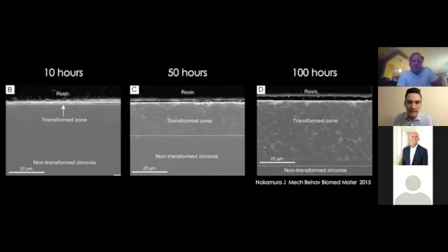We tried to study it, and I was interested in it. And the crowns that we got back from wearing in the patient's mouth for a year, we sectioned through them and tried to see any surface cracking, and we couldn't even find it. It was too small to even see. So I don't get too excited about low temperature degradation.